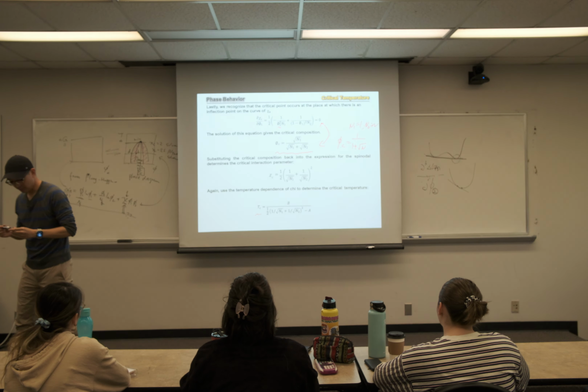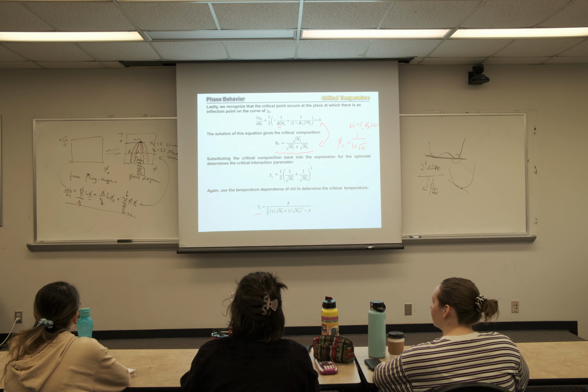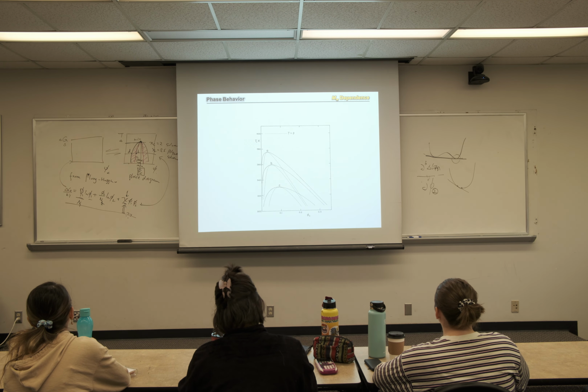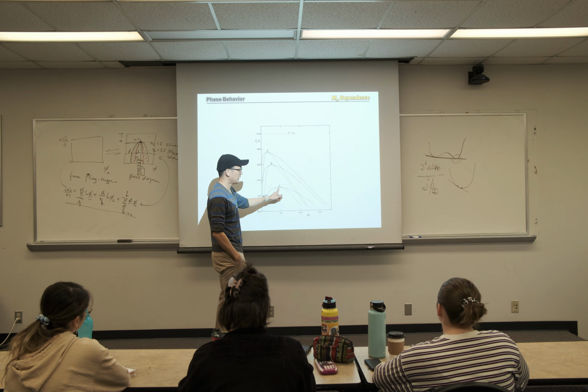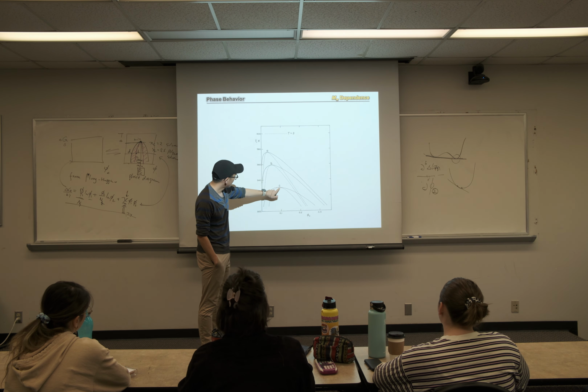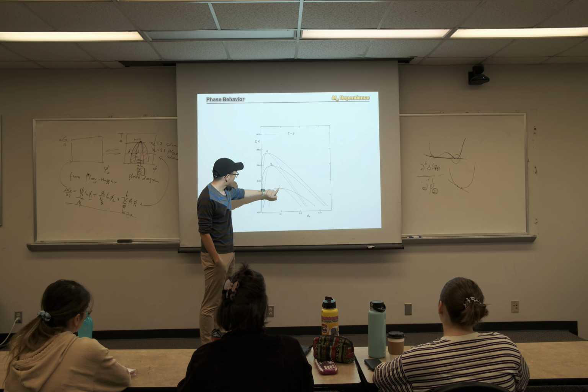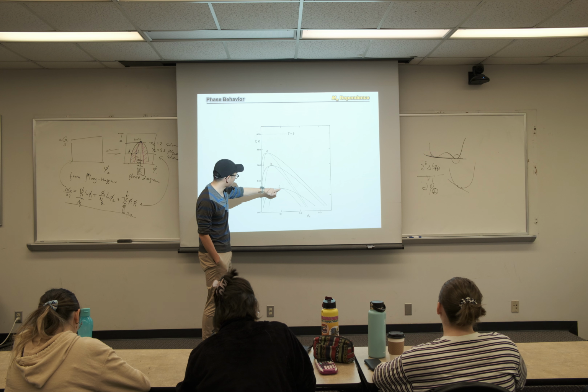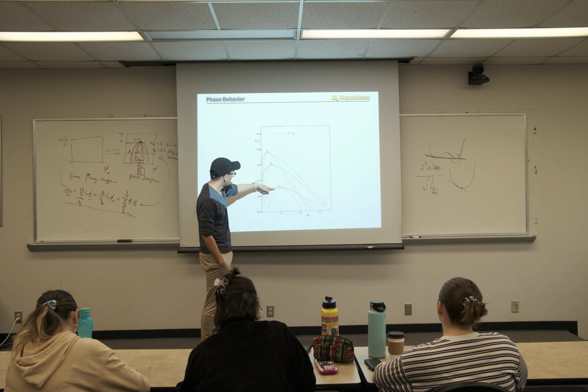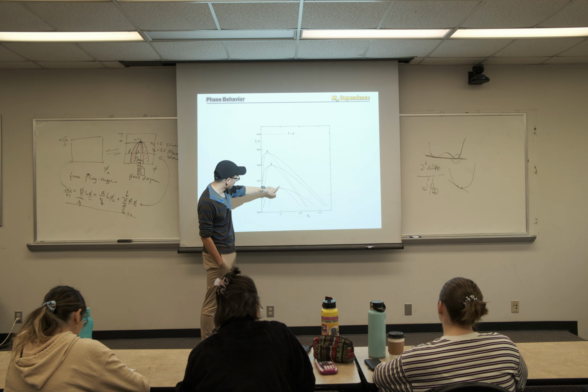Okay, so your phase diagram will not be symmetric, and that's what you have seen in some of the examples. This is a phase diagram more common in polymers. This would be the critical point, the highest point you have. So you can have the critical temperature this way, that is Tc, and you can have phi c this way. This tells you the critical concentration. So when we increase the molecular weight of your polymer, your phase diagram will shift.